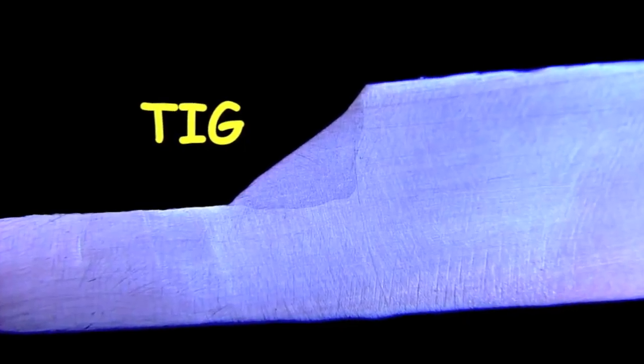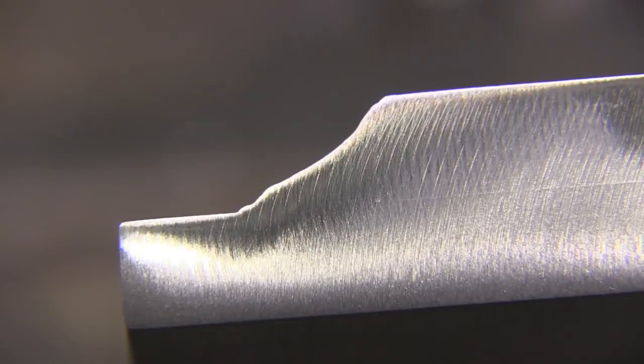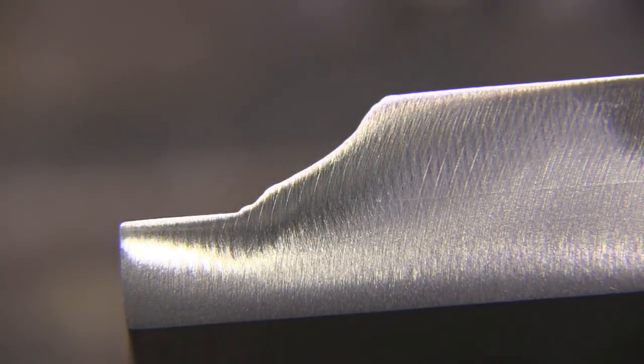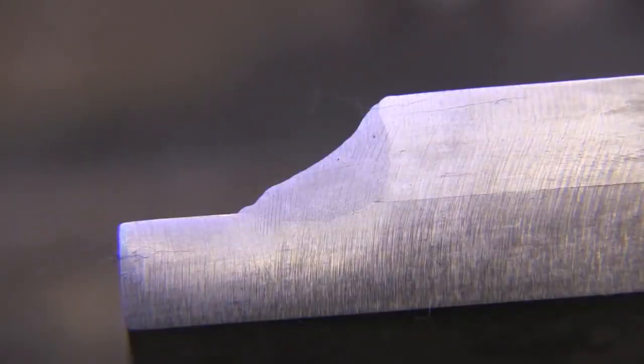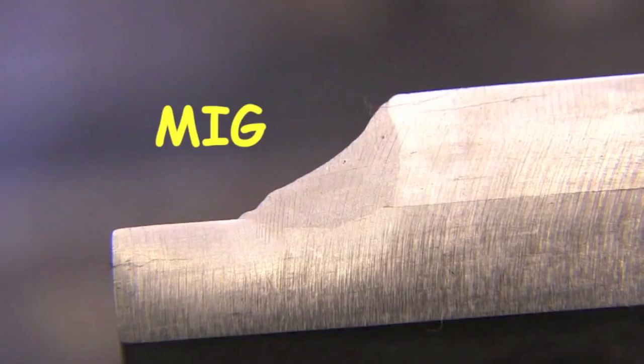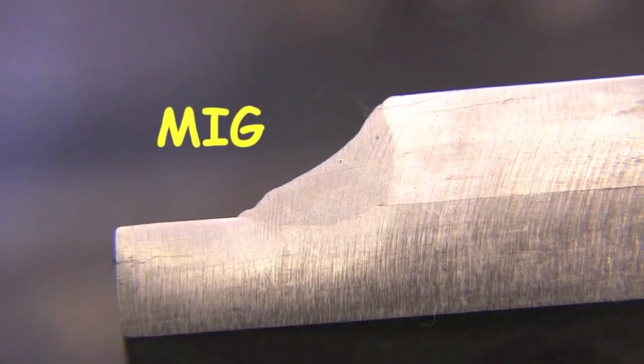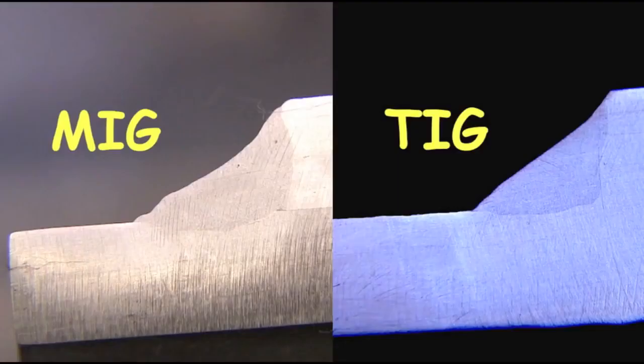And so that's the TIG joint right there. Nothing glaringly wrong there. This is the MIG joint, the MIG weld. Could have polished it a little bit better, but we'll get a result here anyway. And right away you can see just a couple of fine pores, a little porosity, but the penetration is pretty good. Not hugely different than the TIG weld. Aside from those two small pores, the welds are very similar, and the time is not hugely different on these two welds. So that's just good information to have in making a choice on which process to use. Again, in part 2, we'll use the spool gun because we're in the field and it just makes more sense.